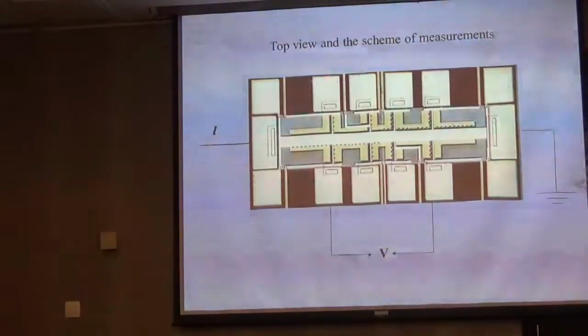Now here is the top view of the sample. Electrons live below this white track, that's our gate. So we apply current between source and drain, and measure voltage between two potential contacts. It's standard. Then we divide voltage by current, we get resistance. And we want to see what's going to happen with resistivity at low temperature.